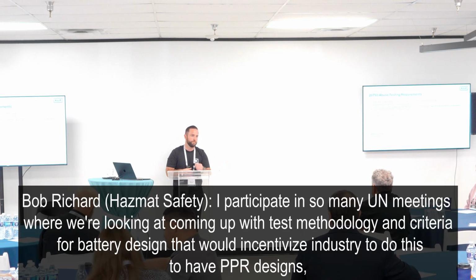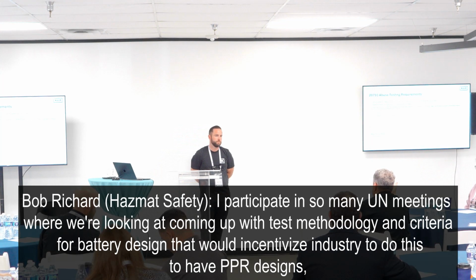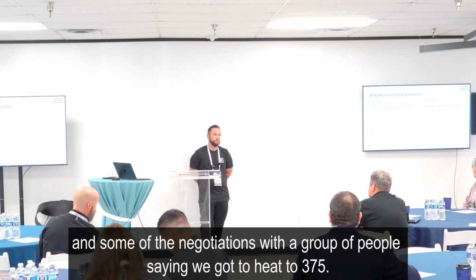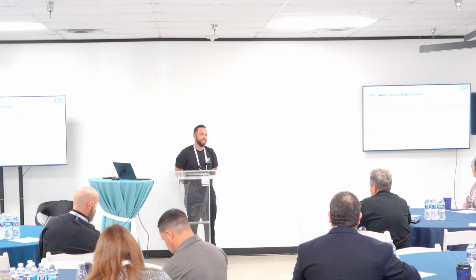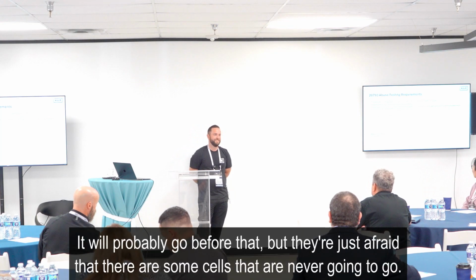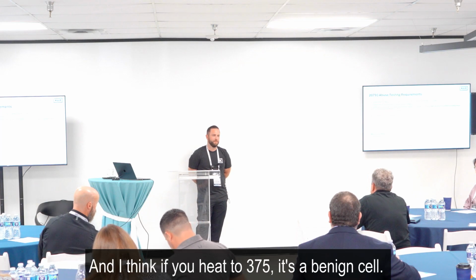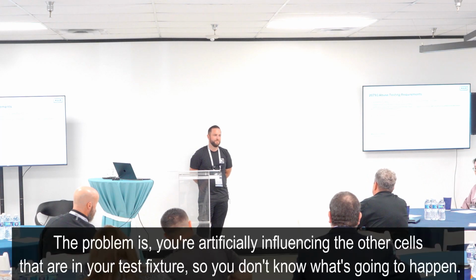Yeah, because I participate in some of the UN meetings where we're looking at coming up with test methodology and criteria for battery design to incentivize industry to do this kind of PPR designs. And some of the negotiations with this group of people are saying we've got to heat to 375. It'll probably go before that, but they're just afraid there's some cells that are never going to go. And I think if you heat to 375, it's a benign cell. Yeah. You give me a break, right? But the problem is, you're artificially influencing the other cells that are in your test fixture. So you don't know what's going to happen.